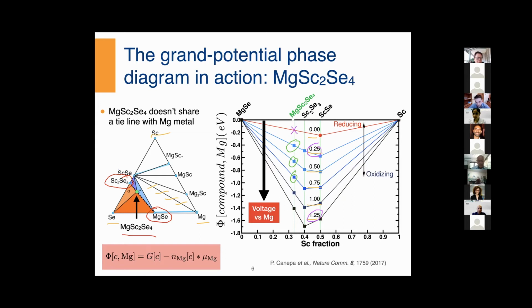The result is twofold. One, you get the bounds of your stability window, which are basically the highest bound and the lowest voltage, which is the cathodic stability limit. So you have a position relative to the magnesium electrode, or whatever electrode it will be, of your reducing stability limit. And then you get an anodic stability limit. And the difference, of course, between these two voltages gives you the window span, the electrolyte stability window that is commonly cited in the literature.